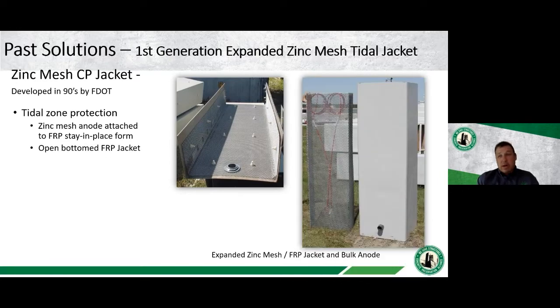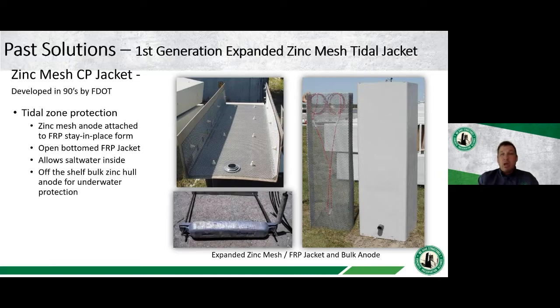You can see here on the right side, the zinc mesh was pre-installed around the pile, then the fiberglass jacket was placed around it afterwards. What ends up happening is the salt water wicks up from the bottom of this jacket. The salt water keeps the zinc in an active state, and it provides galvanic protection this way. 99% or the majority of these jackets also used a bulk hull zinc anode. This is just an off-the-shelf zinc anode that was used on boat hulls, and it's attached to the bottom side of the jacket. This protects everything in that wet zone.